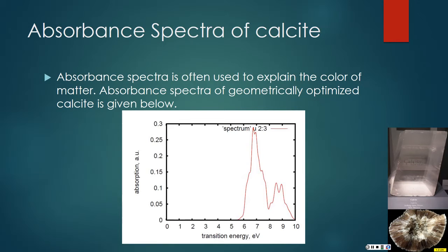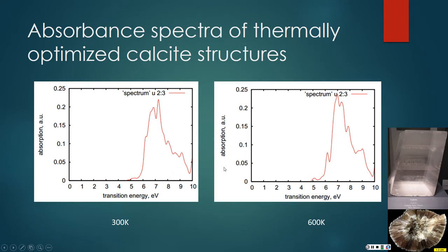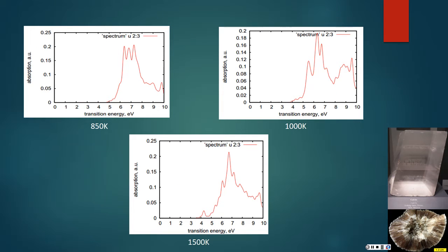Now the absorbance spectra. It is the light matter interaction. This is the absorbance spectra of our optimized calcite. The peak is in the UV region. After doing the MD, if we look at our absorbance spectra, there is not a significant change in the spectra, but the population distribution of the spectra is slowly moving towards the visible region. And if we do the MD at higher temperature, we hope that we can get the peak in the visible range, so that at that time we can get the color of the calcite.